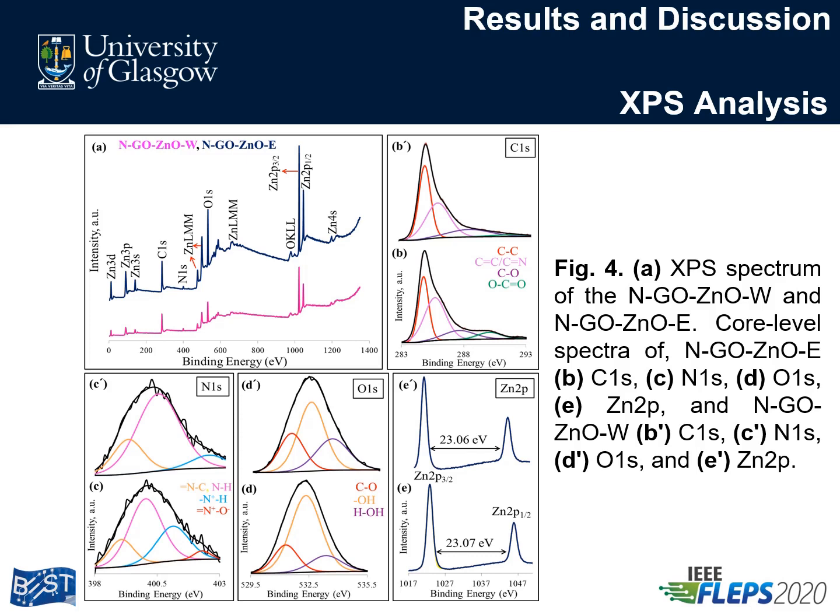Similarly, the nitrogen spectra of both nanomaterials exhibited distinctive peaks at their respective binding energies, which revealed the presence of pyrrolic nitrogen, pyridinic nitrogen, and graphitic nitrogen respectively. However, the nitrogen spectra of zinc oxide nanorods prepared in ethanol solution showed an additional peak at 402.38 electron volt, which indicates the presence of pyridinic nitrogen oxide.